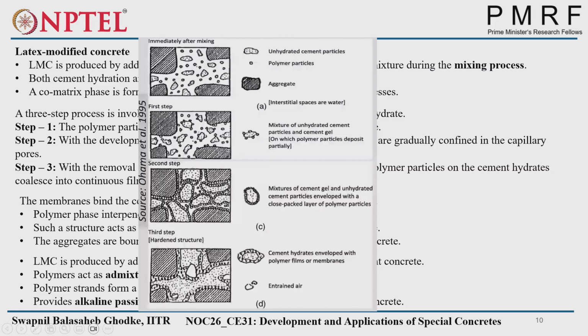So if you see this image properly, this is after the immediate mixing process. These larger particles show the unhydrated cement particles. Smaller rounded ones show the polymer particles, and these lining ones are the aggregate particles. When the further first step, that is mixture of unhydrated cement particles and cement gel. Unhydrated cement particles and cement gel are there, meaning the hydration process is continuing. At that time polymer particles will surround that or attach around that. After that, once the hydration process proceeds further, the mixture of cement gel and unhydrated cement particles is enveloped with a close packed layer of polymer particles. You see, polymer particles are closely packed around the hydrated and unhydrated cements and aggregates as well.